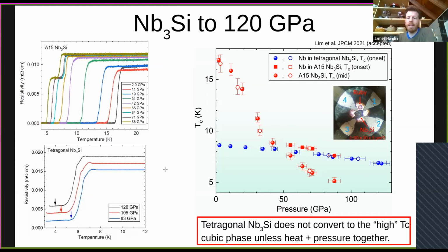And so it seems that tetragonal niobium-3 silicon doesn't convert to the high TC cubic phase unless you apply both heat and pressure together. And I think this is an important point, that if we have some kind of barrier for a transition going one way, it's not a foregone conclusion, but often the barrier will be of a similar magnitude for the transition going the other direction. And so if we really want to recover phases to ambient pressure and have them stick around for a long period of time, we may be interested in systems where we have to use high temperature in combination with pressure. So in this case, room temperature, even though the A15 phase is the stable phase, it was not enough to overcome the barrier and convert the tetragonal to the A15 phase.